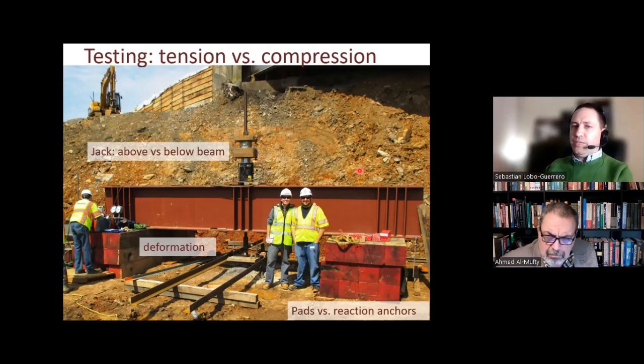So you want to be cost effective, right? But there are also technical considerations that support the tension test even more. If I test in tension, we ignore any end bearing capacity of the micropile. The point bearing, the end bearing, we neglect. But in reality, there is going to be some, right? Either you account for it or not, there is going to be some resistance. When you test in tension, there is no component of end bearing because you are testing in tension. So in some respect, testing in tension is slightly more conservative than testing in compression. And it's also significantly cheaper.